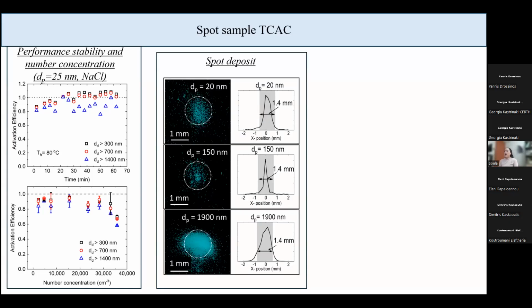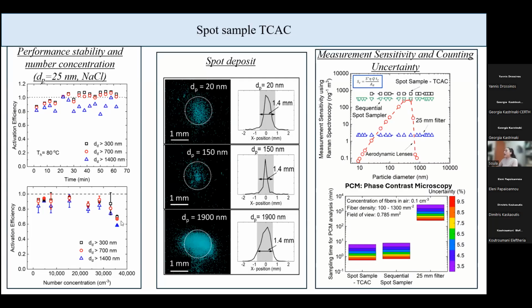Another thing that I tested was the deposition area that we can obtain for different particle sizes. I used PSL spheres from 20 nanometers up to 2000 nanometers, and I got the same deposition area for all of them, approximately 1.4 millimeter diameter. And finally, I calculated the same way as I did before the measurement sensitivity of this collection technique in comparison with other conventional collection techniques. And we can see that we can obtain a better sensitivity when we use the spot sample TCAC.